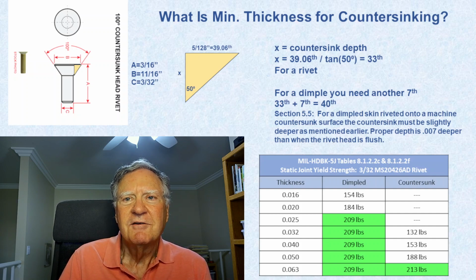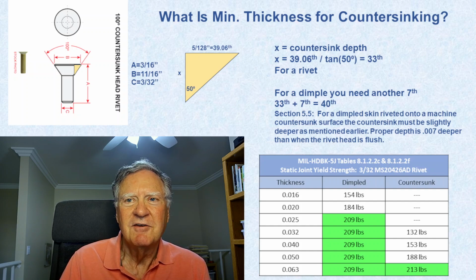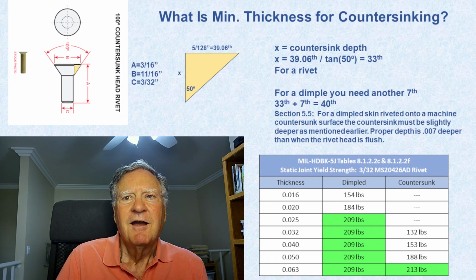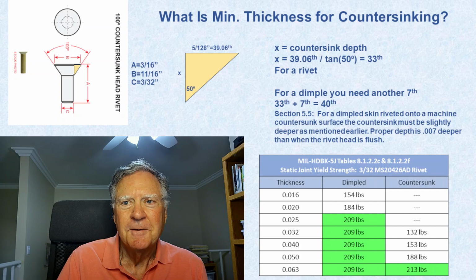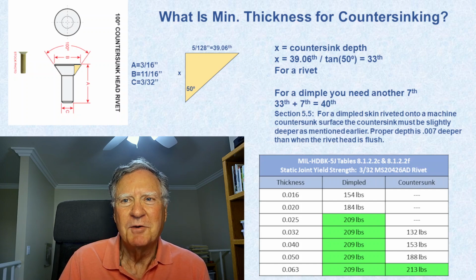And if you go back to section 5.5 of the plans, it says that for a dimple and a countersink, you need to add an additional 7 thousandths to the depth of the countersink hole. So now we have 33 thousandths plus 7 thousandths is 40 thousandths. So for a dimple to sit flush in a countersink hole, the hole needs to be 40 thousandths deep, and if you're not going to over countersink, the metal needs to be at least 40 thousandths thick. And it's not. It's only about 36 thousandths maybe thick. And so that's why we're in a gray area or a problem area.